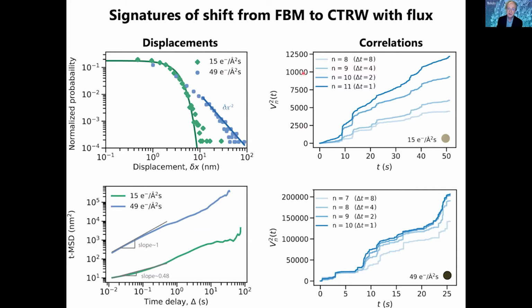We can look at the probability that a particle will be in a similar place at a later time. If we do that for different time intervals, 1, 2, 4, 8, what we see is the clear signature of an anti-correlated motion in the low flux regime, which, as I mentioned, means that every so often, if the particle moves in one direction, it's more likely that it will move in the opposite direction at a later time. That is very much not the case where the electron beam flux is very high. So this method has allowed us, in a reasonably objective way, to take a vast amount of trajectories, classify them, and extract a mechanism for motion.